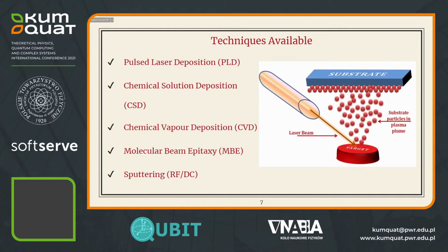During pulsed laser deposition, a laser pulse is passed and hits the target material, which is what we want to deposit as a thin film on our substrate. On application of this laser, atoms and molecules from the surface start to evaporate and form a plasma plume. Within the same chamber, a substrate is placed at a 45-degree angle. When these molecules evaporate, they deposit on the substrate, forming an epitaxial thin film.